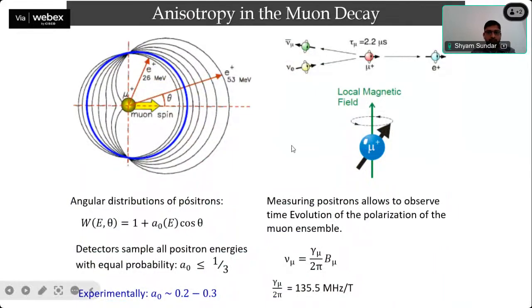What happens, for example, is this is the local magnetic moment in your material, and this is the muon. When the muon goes into the material, it starts to precess around the local magnetic field, and within a lifetime of 2.2 microseconds, it decays into a positron, which we detect. Measuring these positrons allows us to observe the time evolution of the polarization of the muon ensemble. Not just one muon: we have to collect millions of these decays, millions of muons, and then we see their decay and have the time evolution of the polarization of the muon ensemble altogether. So we get the average change in the muon polarization as a function of time, and that provides us the details about the magnetism in the system.